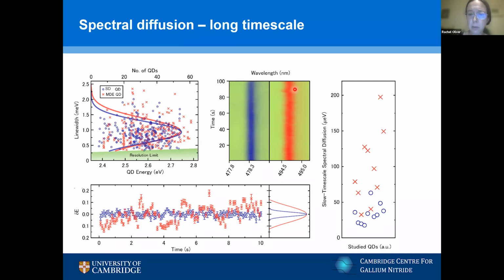So it looks quite a lot better. Trying to quantify that a bit, we can measure the variation of the energy and how much excursion from the average energy we see and how frequently that occurs. And what we're measuring here is the average size of the jumps that we see for the strain-driven and the droplet epitaxy dots. And that's giving us nice low values, particularly for the strain-driven dots.